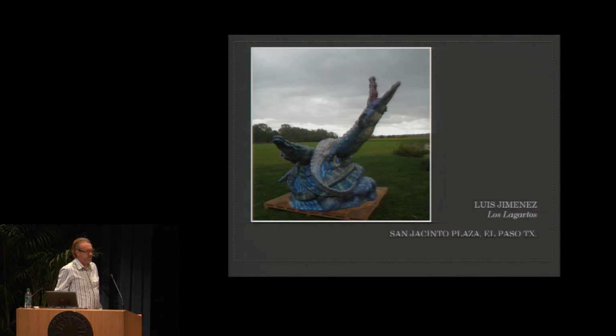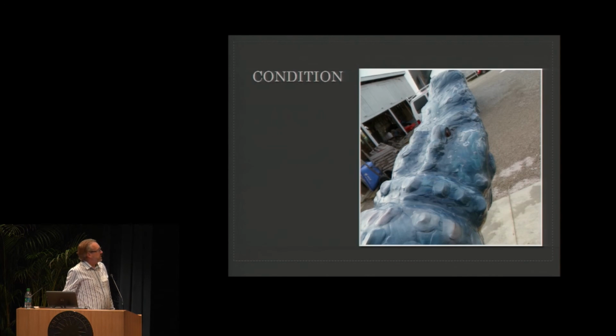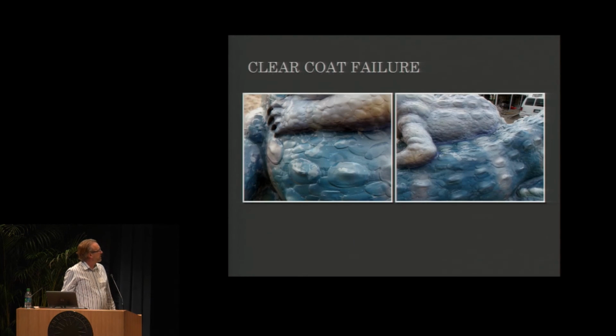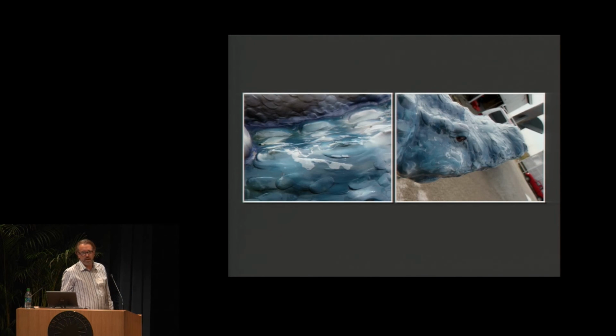So the first thing I used it on was a Luis Jimenez piece called Los Lagartos. The piece had a failed clear coating over an automotive paint. What was happening was the clear coat had failed, was causing severe degradation to the underlying base coat. So to recoat this, we had to remove that top coat. You can see how bad it was.